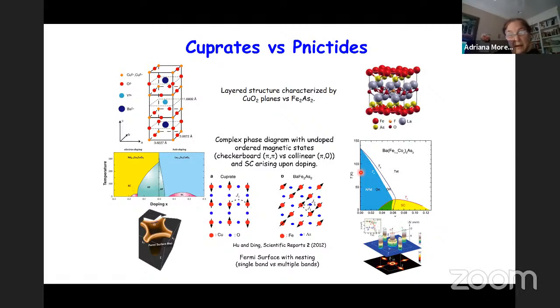The pnictides are bad metals, and they have this pi0 magnetic order, and the reason is the hoppings. In the cuprates, the nearest neighbor hoppings are stronger than the diagonal hoppings because of the presence of the oxygens in the links, while in the pnictides, as I already explained, both J2 and J1 are comparable.